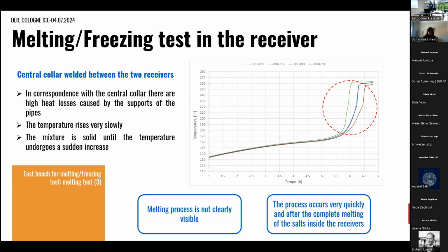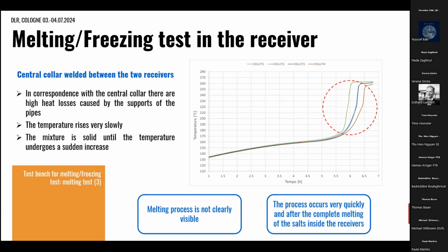Instead, in the central collar, the collar welded between the two receivers, we can see that the melting process starts after the salt has melted inside the receiver. This is due to the fact that in this section the heat losses are very high because it is the support of the pipes, so the heat losses increase. The temperature rises very slowly at the beginning of the process until suddenly the melting starts and goes very, very fast. In fact, the melting process is not clearly visible, and this is also due to the fact that the salt in the two receivers is liquid, and so accelerates the melting of the salt inside the central collar.